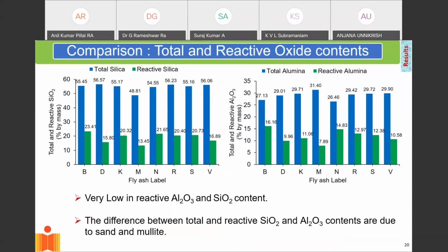But then we started looking at what are the differences, and I will show that to you with this bar chart here. These are the fly ashes collected from the different thermal power plants. And what you see here, the blue lines indicate the total silica. I have already shown that to you in the tabular form. The green lines are the silica that are present in the reactive form. And you can see the differences now. While the differences in the blue lines are not significant, basically the variation is not very large, you can see the green lines, they're much smaller. So when I have something in the range of 50% of total silica, the reactive silica content varies, and it's actually much smaller than the total silica content. So when I'm looking at clinker replacement, when I'm looking to replace cement with this fly ash, only a small percentage of the fly ash is useful in that regard.